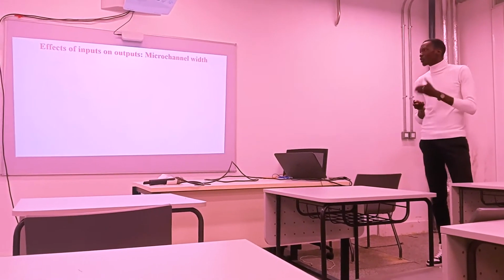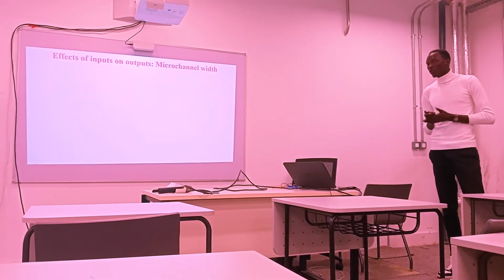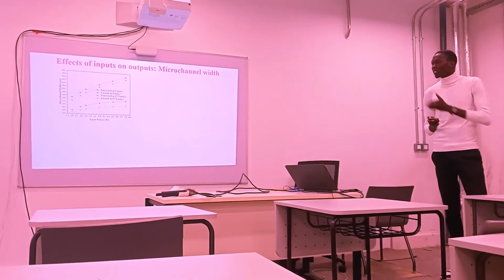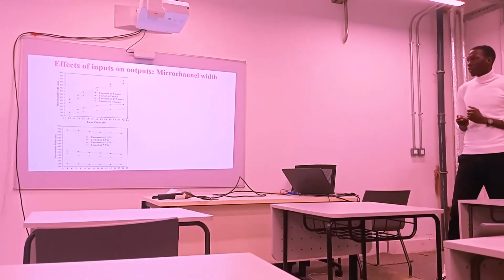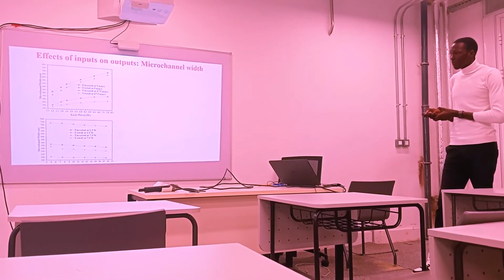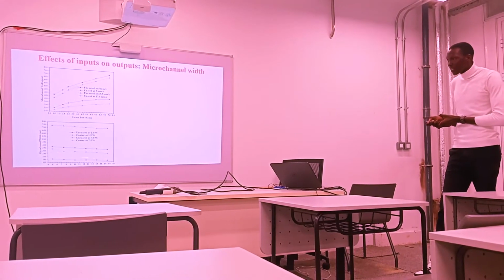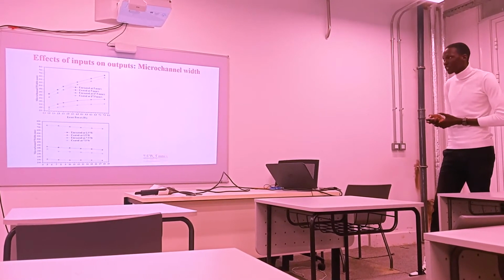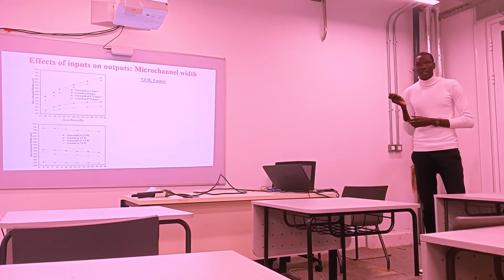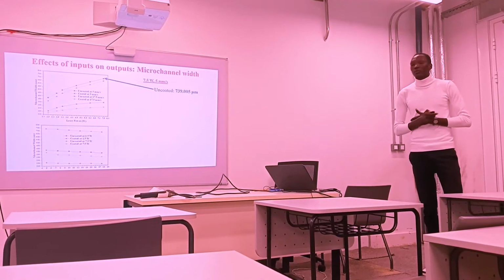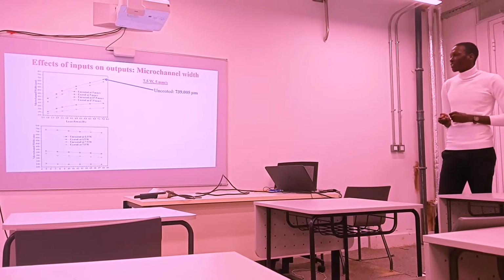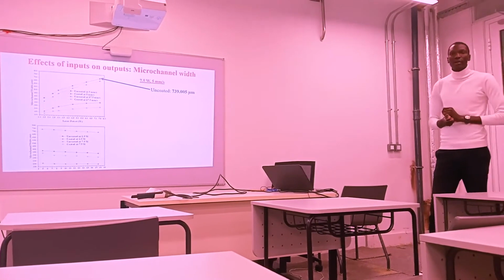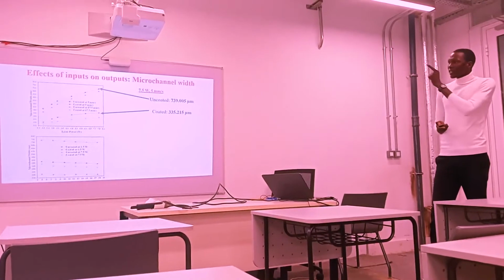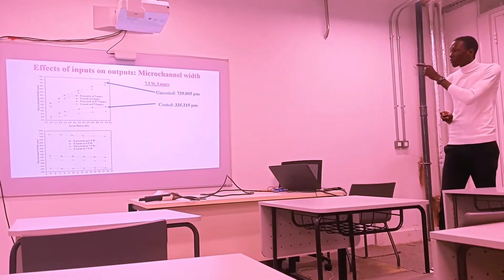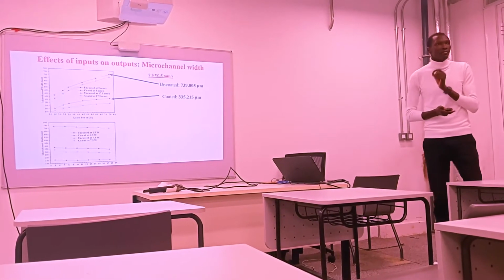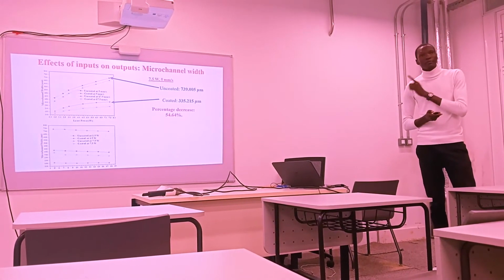And then we were able to plot the graphs to indicate the effects of the inputs on the outputs. We started with the microchannel width. This is the plot of the width against laser power. Then this is the width against speed, the scanning speed. Now, at the maximum power and the minimum speed, this is what we got. For the uncoated, the value was 739.005 micrometers. At the same condition, for the coated, the value reduced to 335.215 micrometers, a percentage decrease of 54.64%.